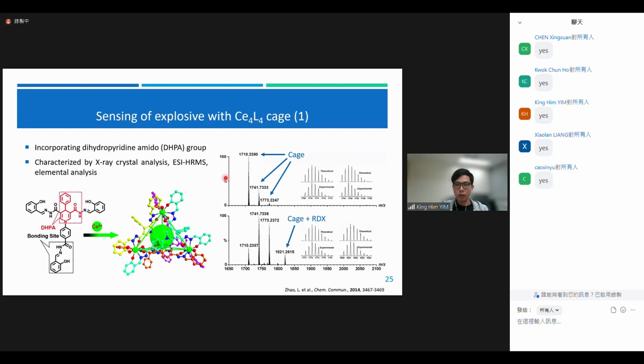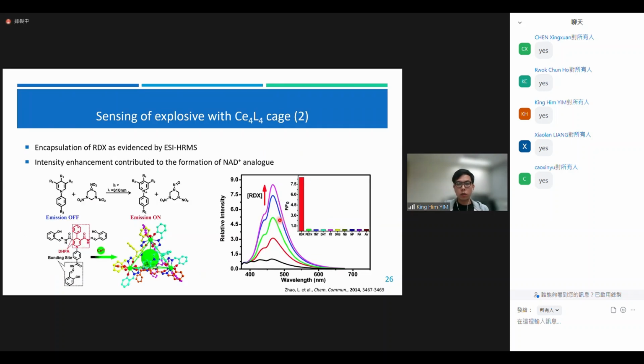And on the right-hand side, it shows the MS peak corresponding to the cage, and also the encapsulation of the explosive called RDX. This peak is very important because it confirms that the encapsulation between the cage and the RDX is in the ratio of 1:1. So they further studied the sensing property of this explosive.